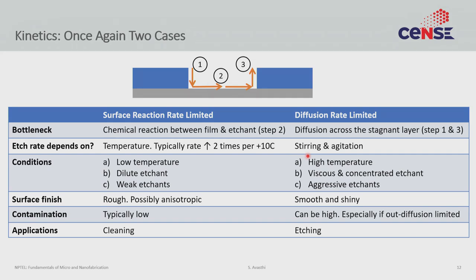If you are diffusion rate limited, stirring and agitation tend to have an effect because these are things that make diffusion go faster or slower. Depending on how much stirring and agitation you do, your etching rate can be slightly different. The advantage is that this provides a method to make your etching rate faster. The disadvantage is that non-uniformity might crop up — it is very hard to get stirring and agitation effects to be uniform across wafers, especially large ones. For a 12-inch wafer, swirling the beaker creates uneven motion at the center versus the edge.